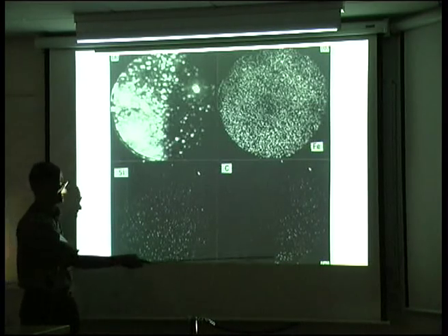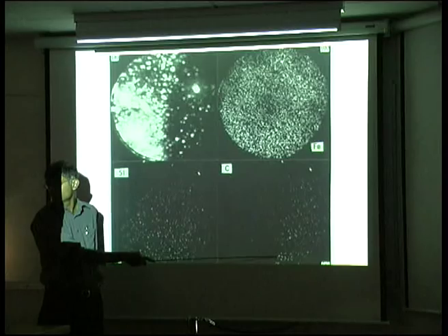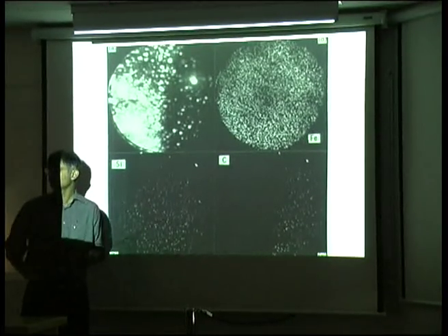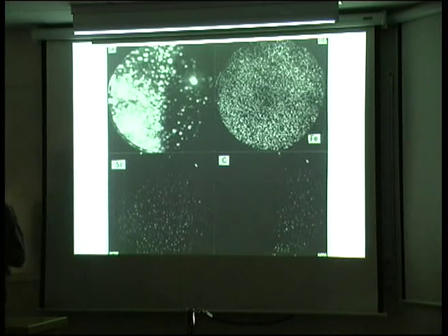But notice this. Can you see that the carbon atoms are on one side? Yeah, they are basically in the austenite. But what this experiment seems to indicate is that carbon is redistributed during transformation. But we need to question that, because at the temperatures where bainite forms, the carbon could escape very rapidly before we can do an experiment. So it may be a completely diffusionless growth, but the carbon will escape before we can do an experiment. Thanks very much. Can we have the lights back on?